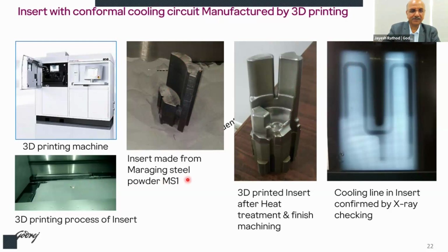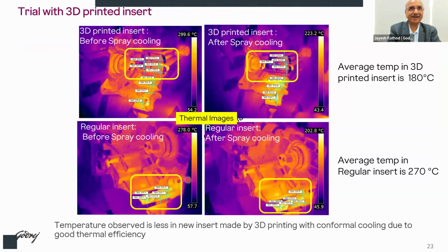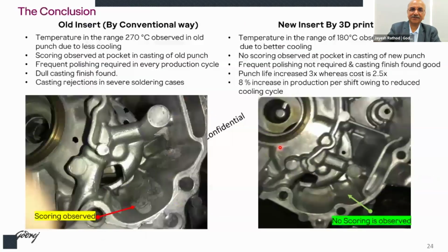So with this, the insert has been made, and our story doesn't end here. Now we have to actually test it, like whatever we have seen in theory, and see what type of benefit we get. So we have made a case study. When there is a regular insert which is normally being used, the average temperature was 270 degrees centigrade in this area, whereas with the 3D printed insert, it came down to 180 degrees centigrade. Because of this temperature difference, the soldering problem has been resolved because of good thermal efficiency here.